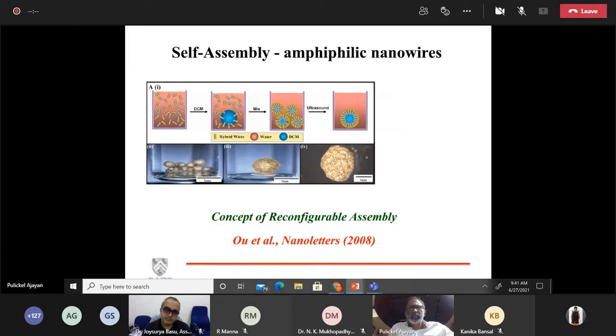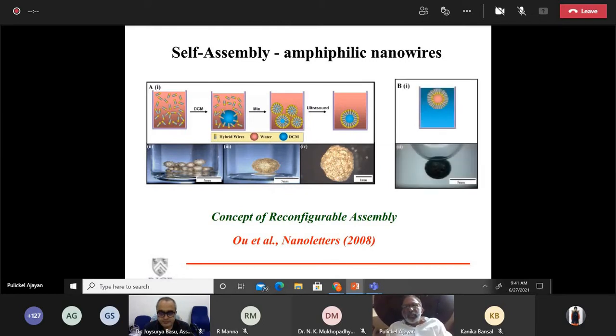And here is an interesting example of using something like that. So what we did was to demonstrate that these hybrid nanostructures could assemble in very different ways depending on the environment that it is in. So in some cases, you can make it assemble with all the gold side facing out, or you can do the reverse by creating the carbon on the other side, by using this amphiphilic character of these nanowires. And this leads to this whole concept of reconfigurable assembly.